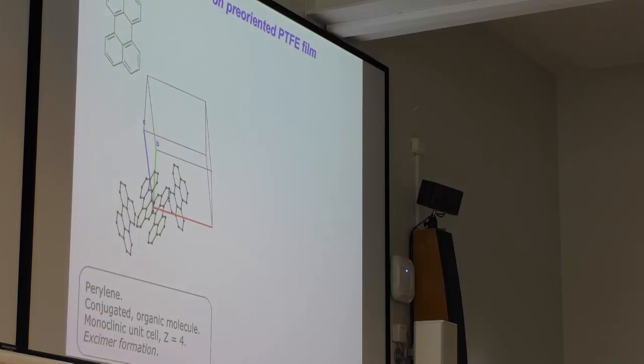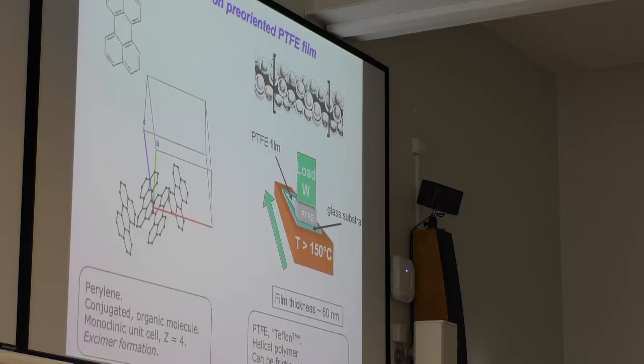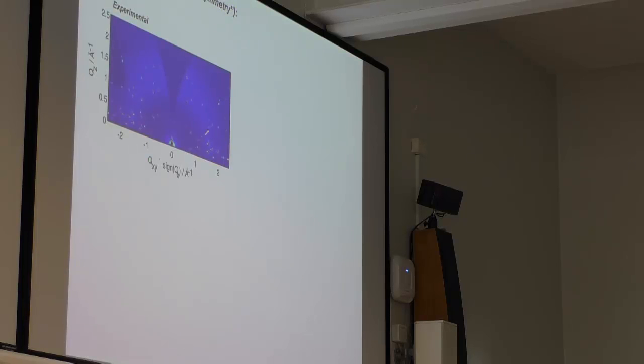So as an example, this is the small organic molecule perylene, which we can also deposit on friction deposited PTFE, which is famous for being an alignment substrate for a lot of organic molecules. And the scattering patterns can typically look like this. So you can see that this is a very crystalline material, judged by the fact that there are all these strong Bragg peaks, and you can also notice how symmetric the pattern is, meaning that we have this fully randomized in-plane orientation that I mentioned. But you can also notice that there is no smearing of the diffraction peaks radially here, which implies that these molecules or crystallites really have a very well-defined orientation with respect to the substrate, right?